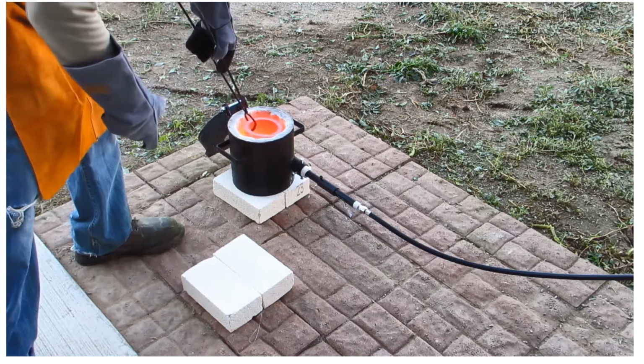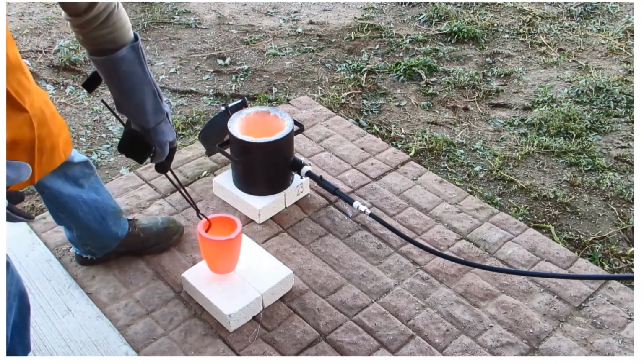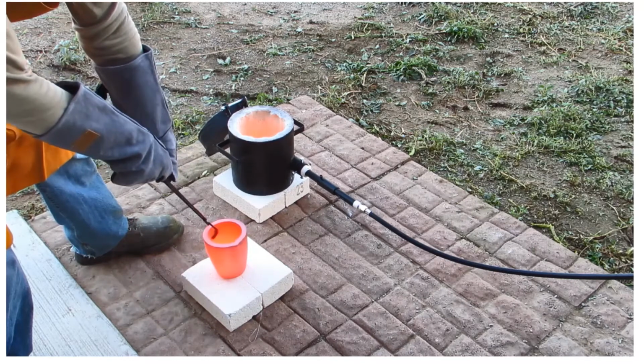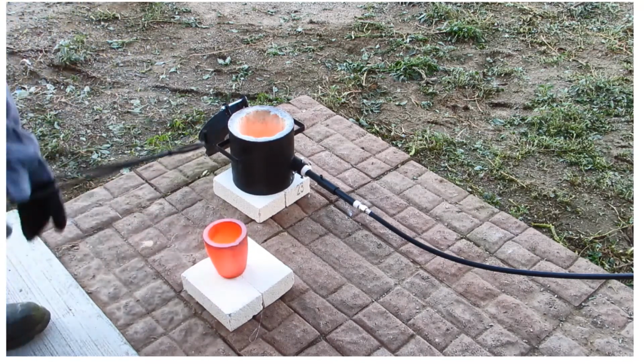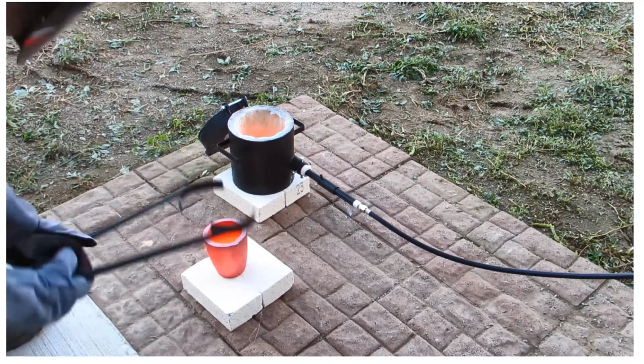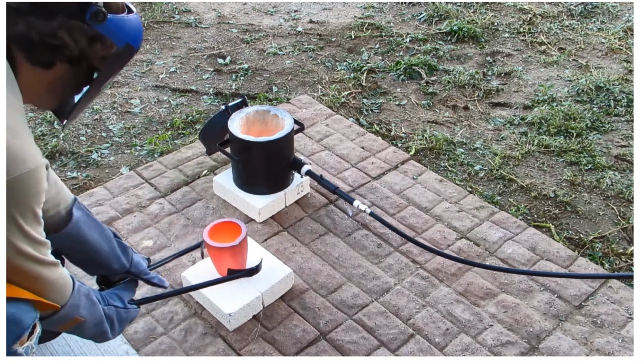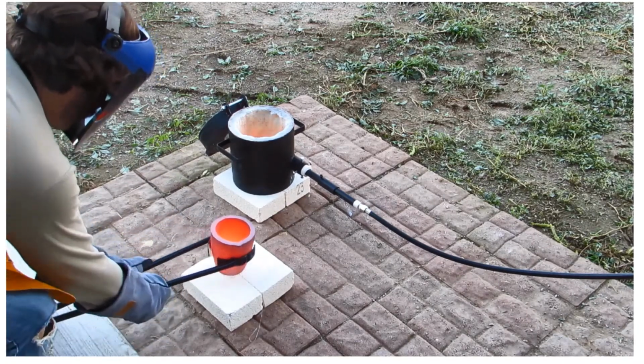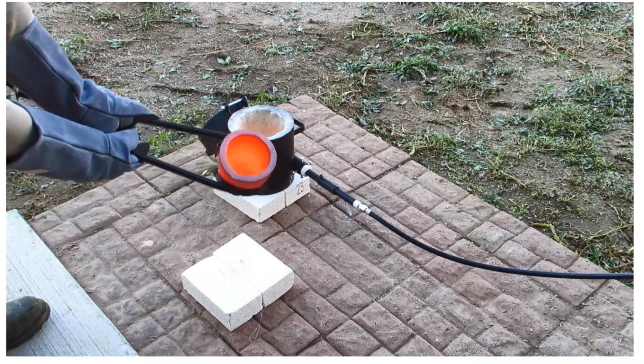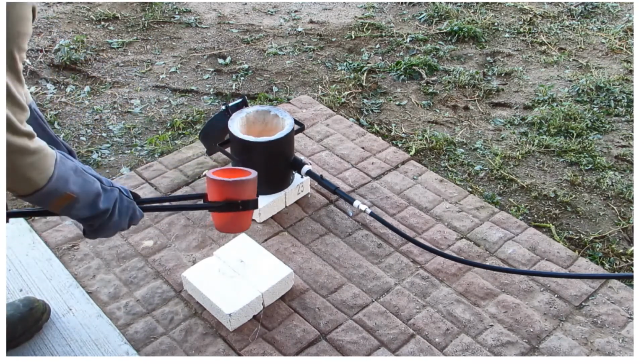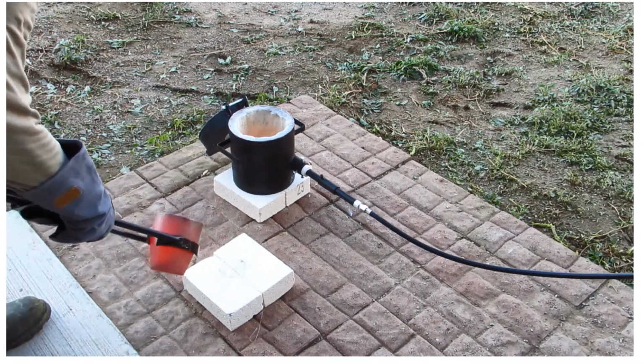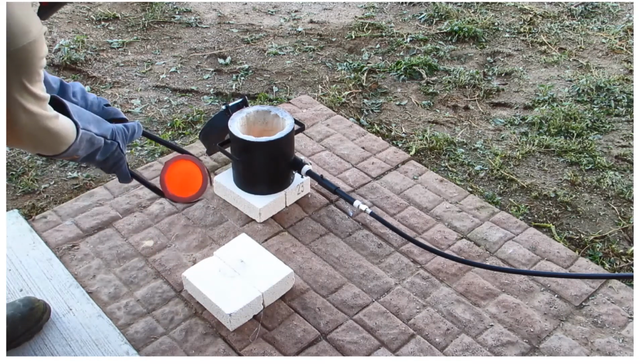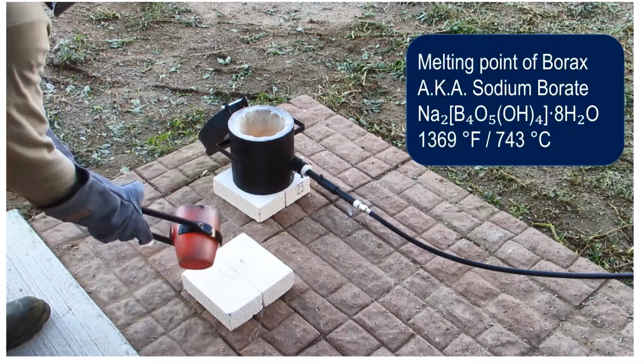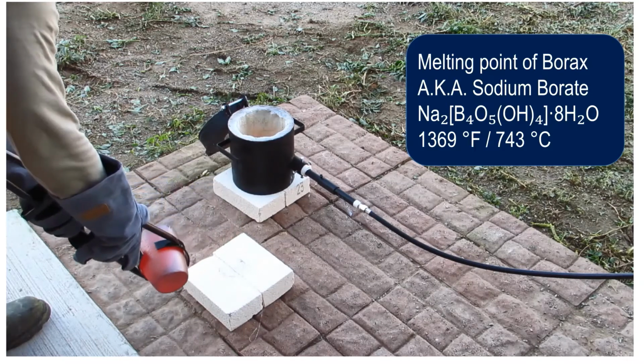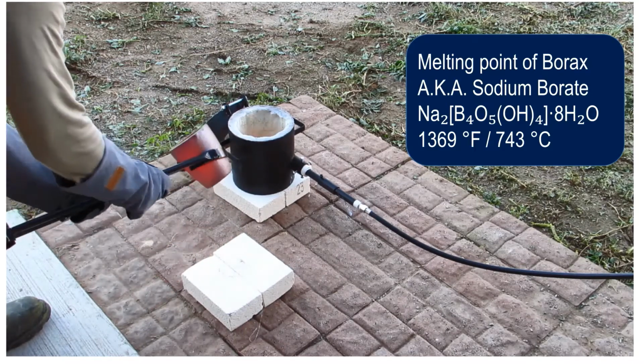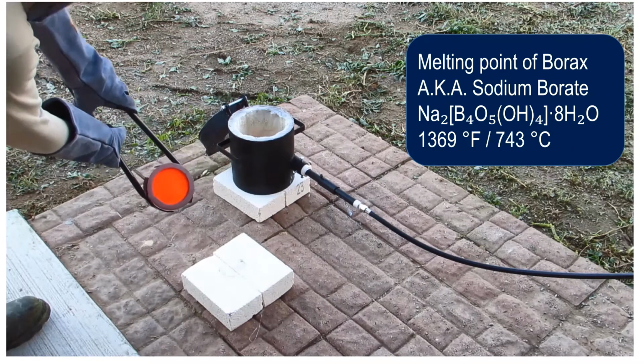I don't believe in pouring by holding the rim of a crucible. I see other people do that, but in my youth I actually broke a full crucible, and that memory has stuck with me ever since. So I use larger tongs to pour and to handle the crucible like I'm doing now. Inside you can see the molten borax. How hot is it? Well, the melting point of borax, also known as sodium borate, is 1369 degrees Fahrenheit, 743 degrees centigrade.